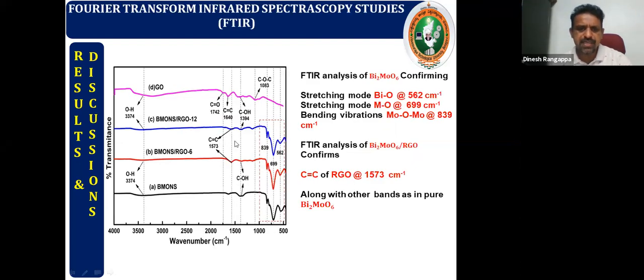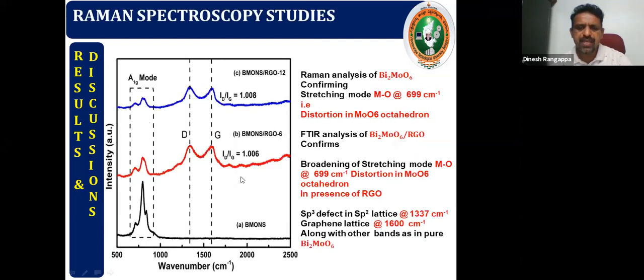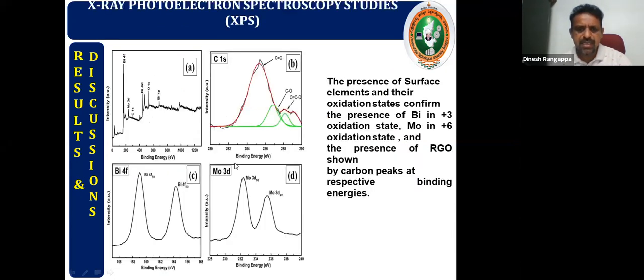So similarly, we studied surface functionality and confirmed the presence of different functional groups on the surface. And Raman spectroscopy shows the presence of graphene sheet, which means we confirm the formation of the heterostructure. And XPS also shows the presence of bismuth in +3 oxidation state and molybdenum in +6 oxidation state, along with the presence of RGO, which is confirmed by the presence of carbon peaks.